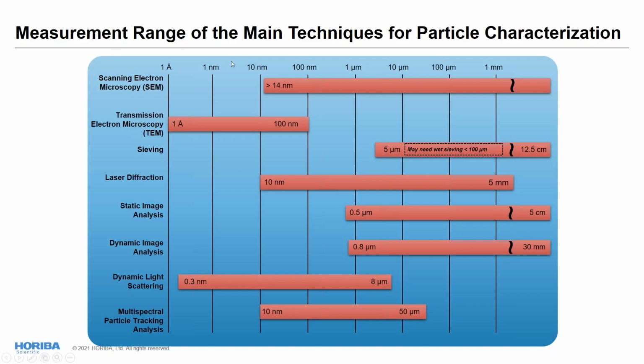And then comes sieving, which is the first technique that was created to measure particle size distribution, which also is a lot of work to do. It has a very limited resolution, because the resolution is limited to the sieves you have. Even if you have all the possible sieves, you're still going to have a very coarse resolution. And for some sieving, when you go to lower sizes, you need to do wet sieving, which completely changes the characteristics of your sample.